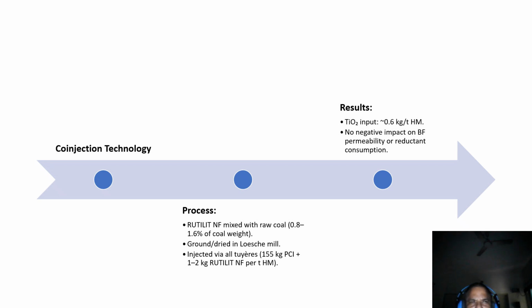To apply Rutilit, it's blended with coal at a ratio of about 1 to 2 kg per ton of hot metal. This mix is dried and finely ground, then injected through all tuyeres using a pulverized coal system. This way the TiO2 reaches deep into the hearth where it is needed most.